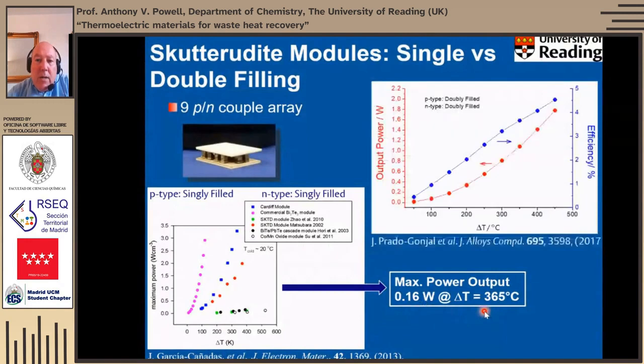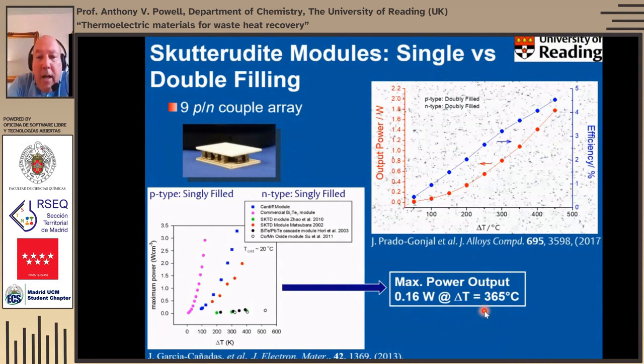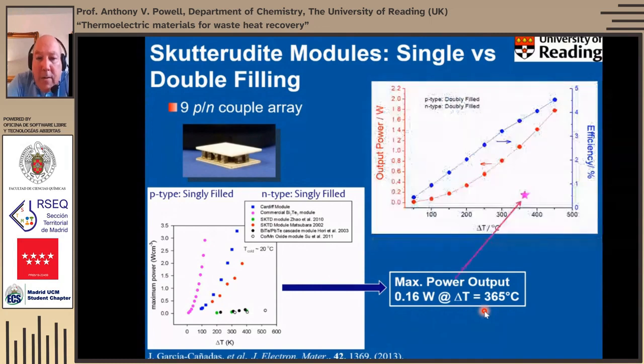So having made the doubly filled materials, of course, we then wanted to see how they performed in a module. So here the N and the P type are both doubly filled, and we can see that the output power is now in watts, so it's not directly comparable with the figure on the bottom there. But if I put the data from the bottom onto the same scale, the maximum performance that we have in the singly filled skutterudites is where that star is. So we've significantly improved from roughly 0.2 watts.